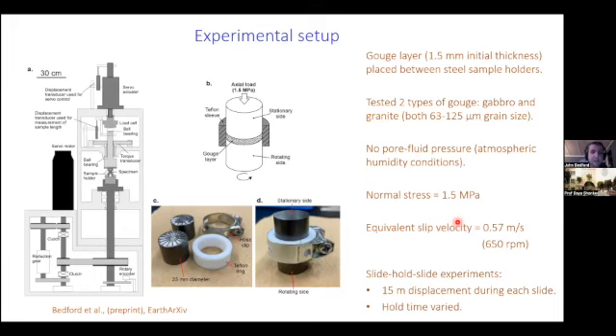So to perform these high velocity experiments, I used the rotary shear apparatus, which is in JAMSTEC in Japan, the Japan Agency for Marine-Earth Science and Technology, where I was based as a postdoctoral fellow for a couple of years. And basically, I took layers of gabbro fault gouge and granite fault gouge and sheared them in this rotary shear apparatus under quite low normal stress at just 1.5 megapascals, and applied an equivalent slip velocity of just over 0.5 meters per second, so approaching seismic slip velocities.